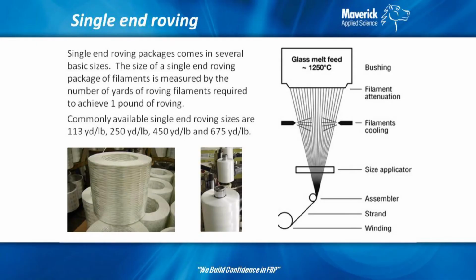113 yield will give you a very ropey pipe. It's such a thick glass that when you stack it all together and make a winding band out of it, a lot of times you'll see bridging because the pattern will be so thick. So a lot of times, unless it's big diameter pipe or big diameter tanks, 113 yield isn't very common. 250 yield is probably the most common that's used out there. And as you get smaller and smaller, if you make 1-inch pipe, you'll use other different end rovings.